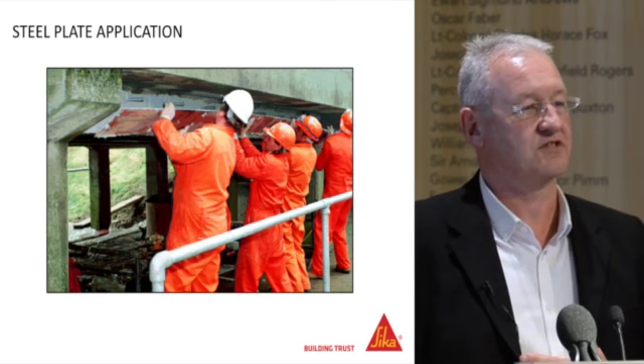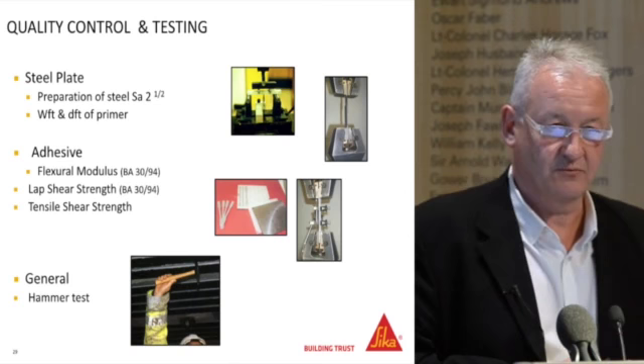Because of the temporary works and pressure applied by the contractor, there is a danger of extruding adhesive out between the plates. We normally recommend applying plastic spacers around 2–3 mm in thickness so that only a controlled amount of adhesive can be extruded. Plastic spacers are used rather than metal ones to avoid bi-metallic corrosion forming in the joint. Then the plates are simply placed into position — from mixing to application you're looking at 40 minutes. Any subsequent drilling is carried out afterwards through the steel, the epoxy, and into the concrete.